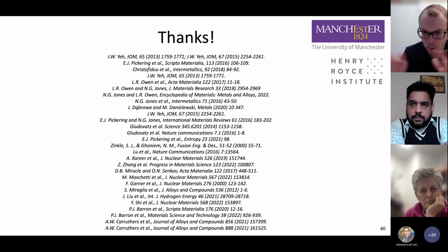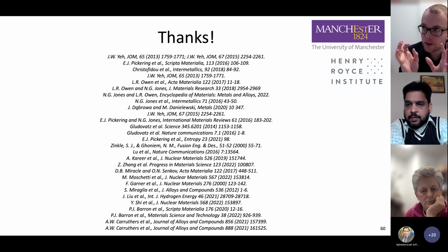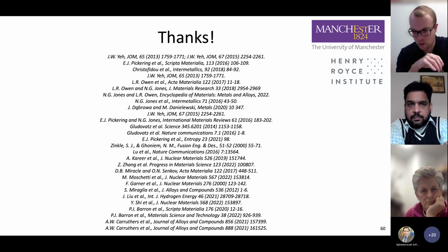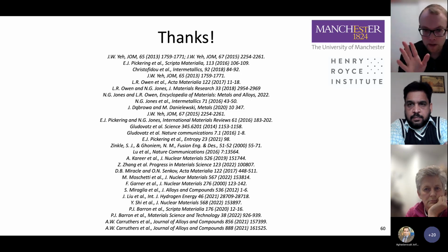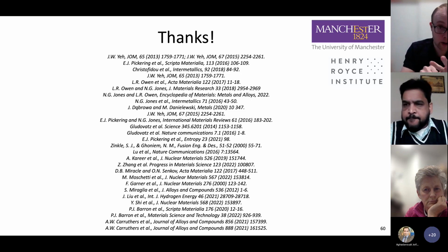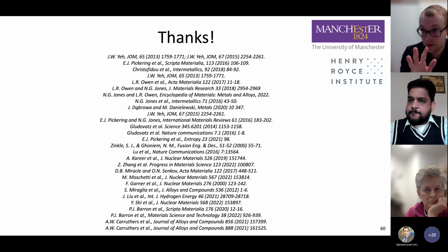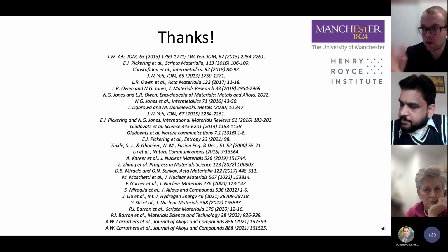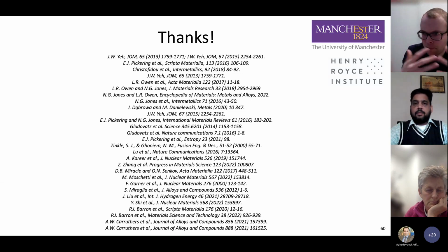It depends on the alloy system and what we're looking at. If you've got the Cantor alloy, for instance, small changes in the amounts of chromium, manganese, iron, cobalt, nickel in that system, let's say plus or minus two atomic percent, don't seem to change the results all that much.